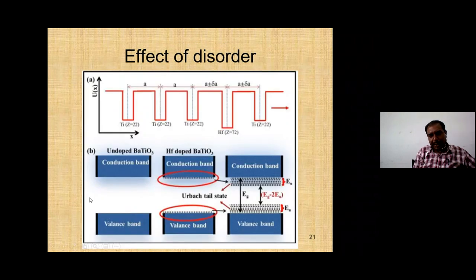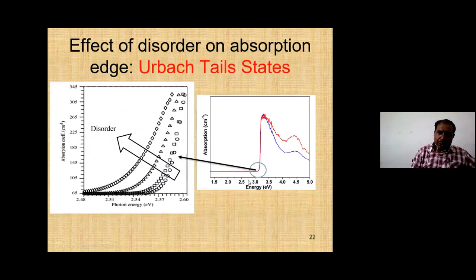Okay, so what exactly happens is the following. You have the valence band and the conduction band. This is the ideal sample, and when you increase the disorder, you get something called tail states near the valence band and near the conduction band in your sample. So these are the tail states. Now if you perform optical absorption spectroscopy on samples having finite disorder, then what you will realize is the following. I have enlarged this particular section in this slide. So what we understand is the following.